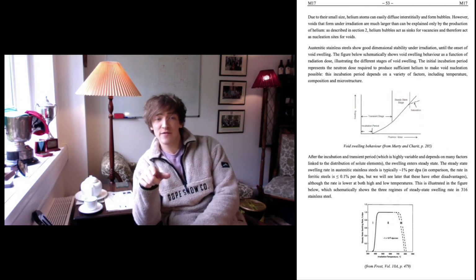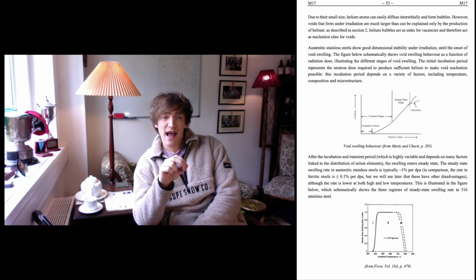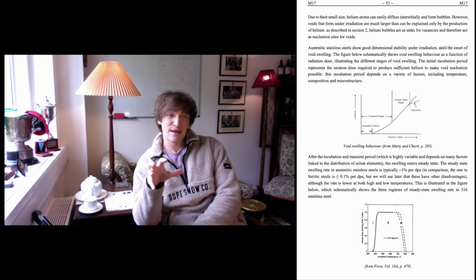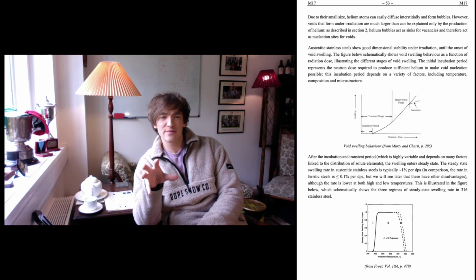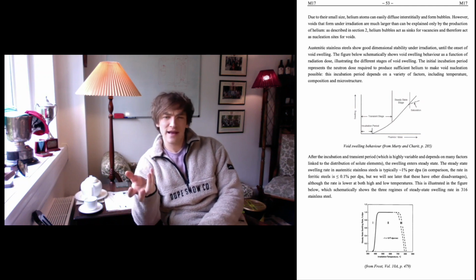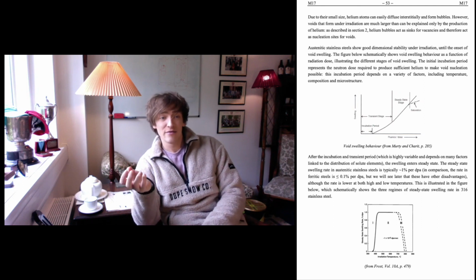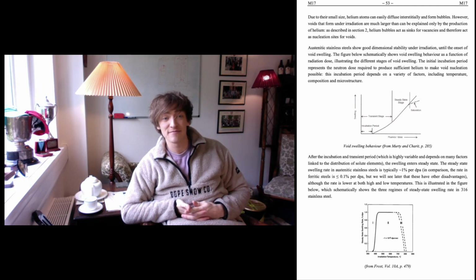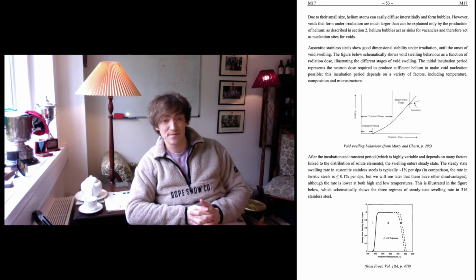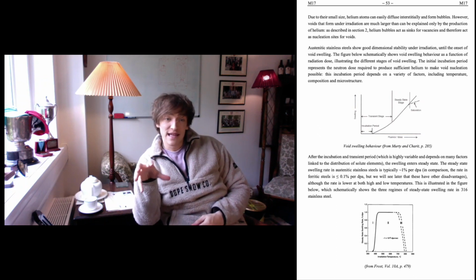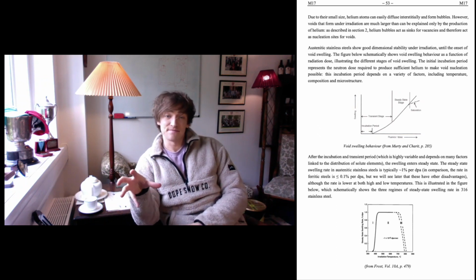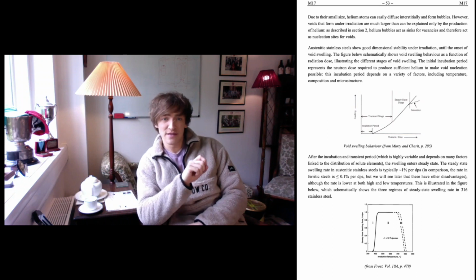After that incubation period, next up you've got the transient stage, and there is where swelling enters steady state. Typically around 1% swelling per displacement per atom, which, to give you a perspective, is much higher than for ferritic steels, which earn themselves less than 0.1% per dpa. So you're getting 10 times the steady swelling rate in austenitic rather than ferritic. And within steady state swelling, you're going to have 3 regimes. And that's shown in the figure at the bottom of page 53.